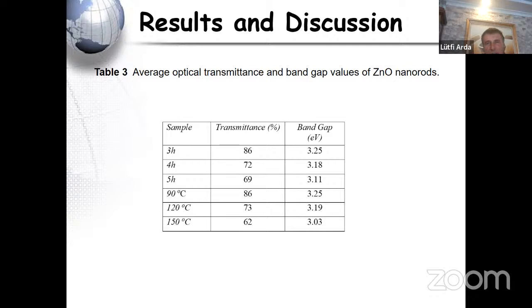According to the table, for the sample grown for 3 hours, the average optical transmittance corresponds to about 86%, indicating that the film is transparent in the visible region. Visible region means it's between 400 and 800 nanometers. This relatively high optical transmittance in the visible region decreases as growth time increases to 5 hours. The decrease in transmittance with the increase in growth time was observed quite frequently in previous